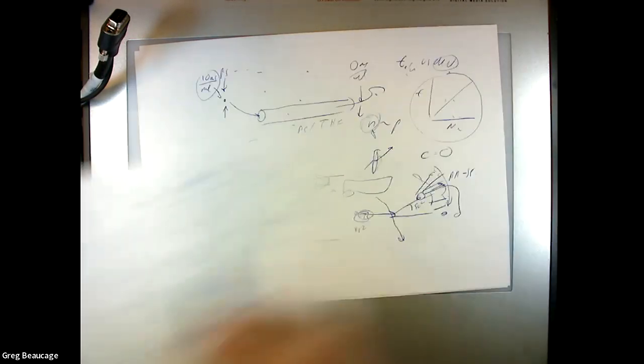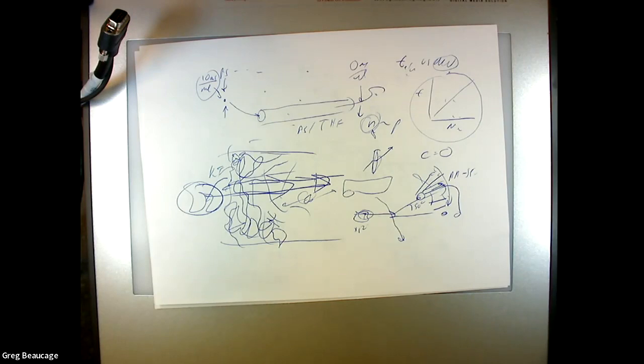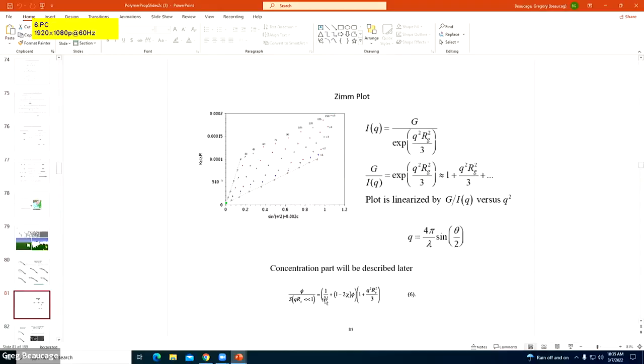But if I run light scattering on this thing, then I can get this n here directly from it. I'm at zero concentration, so there's no chi, and I can get the n directly. From extrapolating to Q0, I just get the molecular weight, and it doesn't matter what moment it is. It's just the number of that monodispersed sample that's coming out. So if I stick an index detector on it, I can get the distribution curve. If I stick this thing on it, I can get the molecular weight of that fraction. And I can tell exactly what my stuff is.